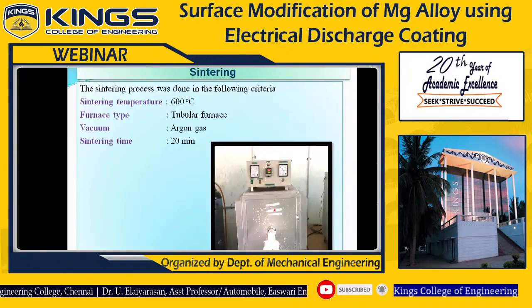After the electrode is prepared, sintering is carried out. Here the sintering temperature is 600 degrees Celsius. The furnace type is a tubular furnace, which is also available in the university. Vacuum argon gas has been used. The sintering time is 20 minutes. After sintering, we cannot take the compacted electrode out of the furnace easily, and it should be cooled in the furnace itself for 3 to 4 hours. After that we can take the electrode from the furnace, pack it in an airtight cover, and further use it for the EDM process.